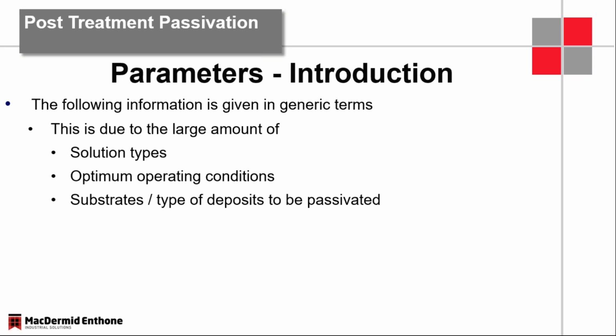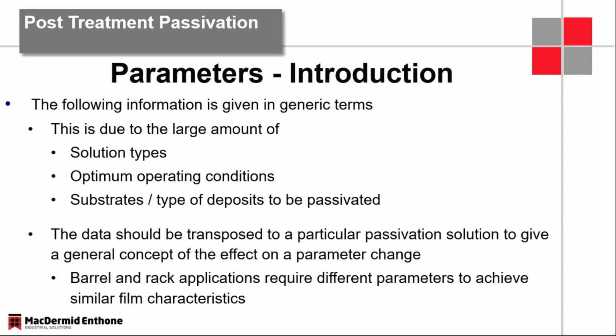An alkaline deposit wants to absorb in a Passivate. An acid deposit is more laminar, and you have to really bite through it in order to get that chrome precipitation. So the operating conditions can be dependent on the substrate as well. So what does all this mean? It means you take your information, you do best practices, and then you adjust to the system that you're doing it with. Barrel and rack, huge differences in operating parameters, potentially, depending on your plating line.